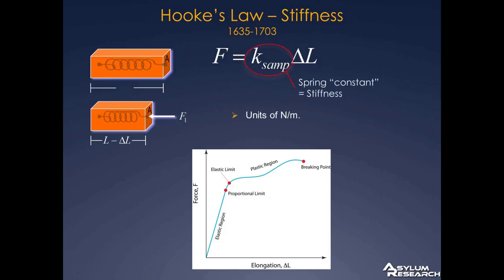The spring constant is also referred to as the stiffness. So in the case of pushing on the sample here, this little orange bar, the spring constant is the stiffness of that orange bar. It's an extrinsic material property in that it depends on the material, but it also depends on the geometry of the structure of the object. So if I change the shape of that bar, turn it into a spring or double the size or something like that, in general the stiffness will also change. We'll talk about Young's modulus, which is an intrinsic material property, and that should not depend on the geometry. So most materials deform by only a percent or so until they yield, until we get to this breaking point here, although some polymers and rubbers can deform by well over 100%.